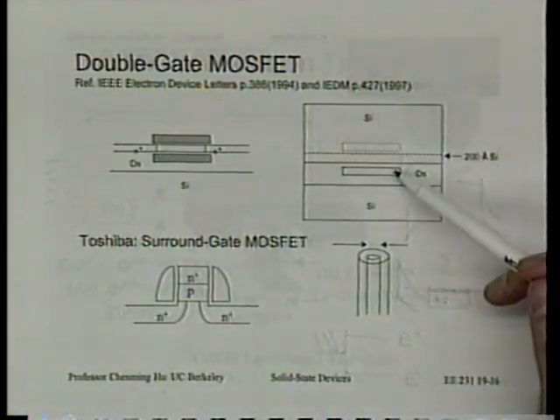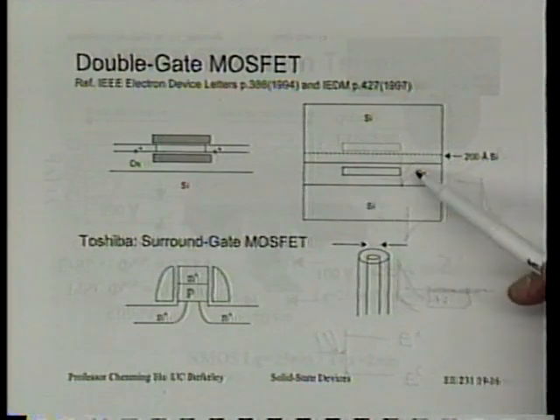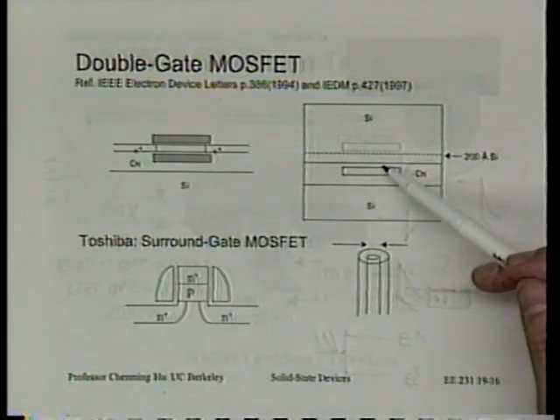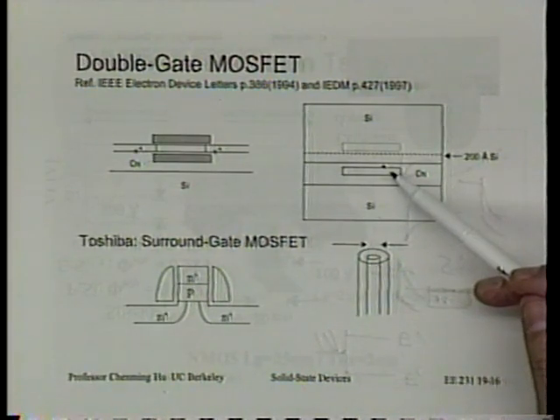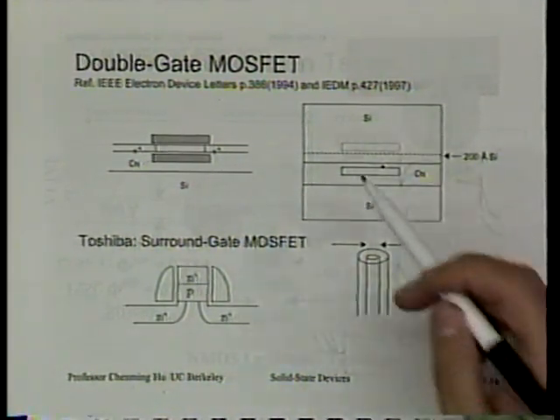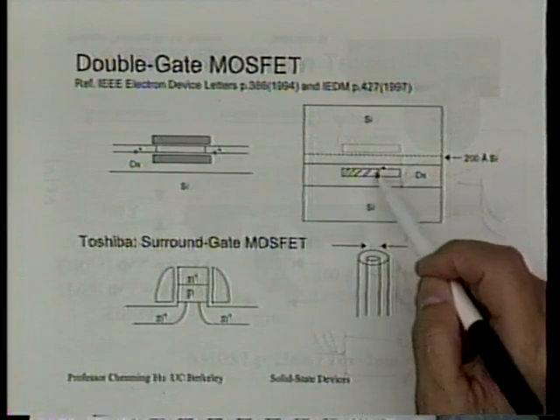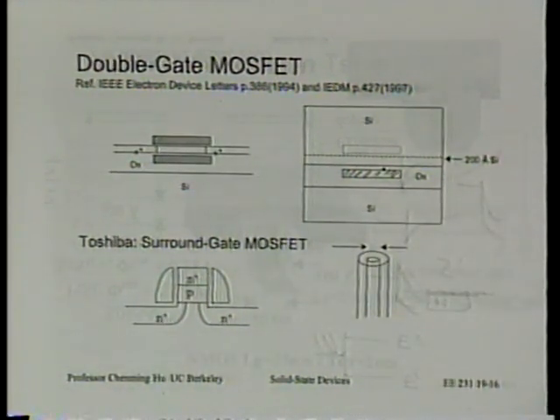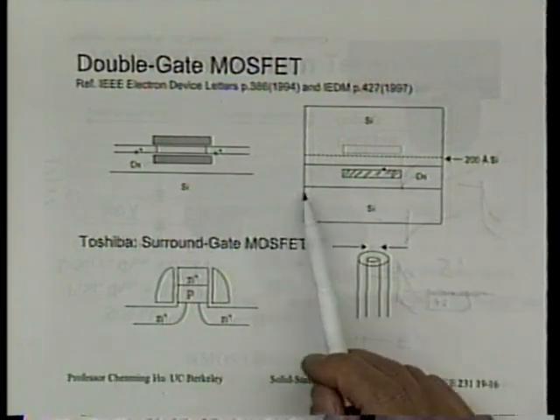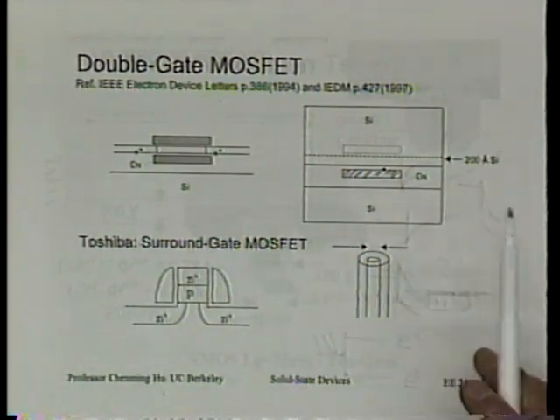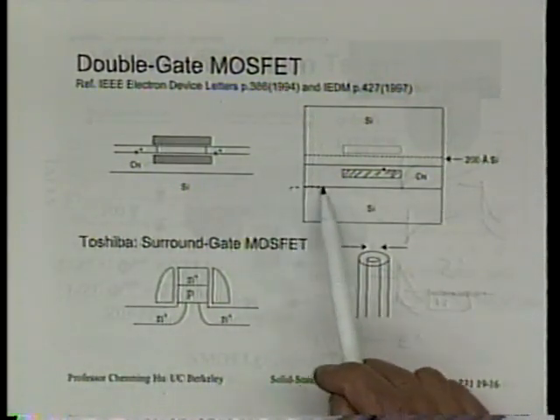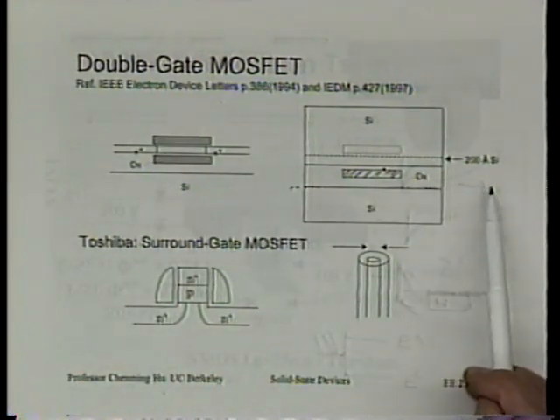You grow some gate oxide, yeah? That's the gate oxide, okay? If you grow the gate oxide, you put on polysilicon gate material and define the polysilicon gate. So this is the polysilicon gate, okay? After that, you will deposit some CVD oxide. You do polishing to get a smooth, flat surface. Are you still with me?